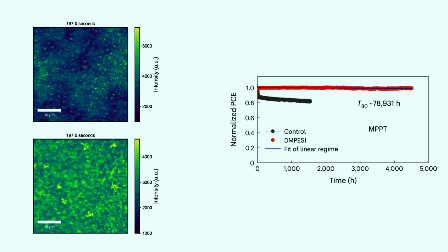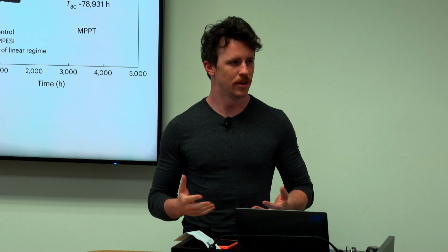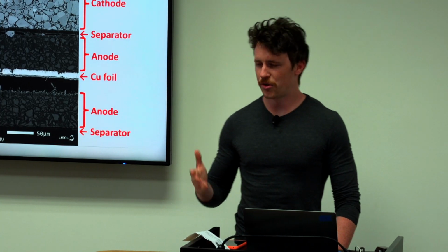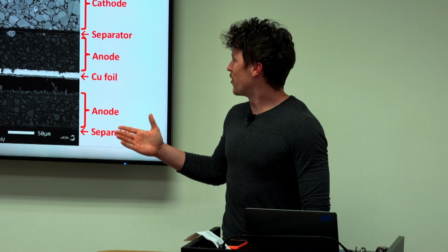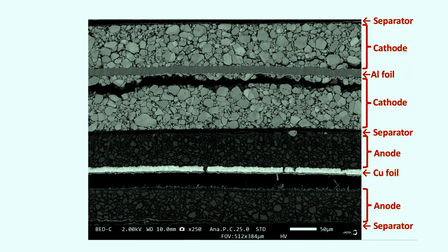So the vision of my postdoctoral work is, can we apply a similar approach to the battery space? The reason I think it's useful is that if you look at a cross-section of a battery, batteries are disordered and messy by design. If you look at any one of the electrode materials, in the schematic that John showed, it's just a nice smooth line, but in reality, it's many microscopic particles wrapped up in some carbon and some binder, and the same is true for the other electrode. So when we're cycling a battery, we're cycling lots of independent little particles that all have their own behavior. And if we could understand all of these during a cycle, then maybe we could build a better model for how to make a better battery.